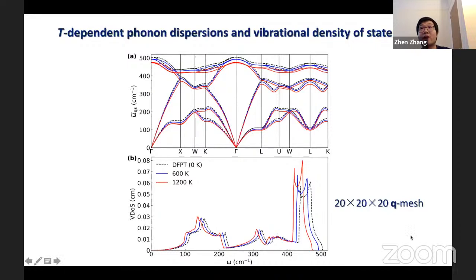Here I show the anharmonic phonon dispersions and the density of states at 600 and 1200 Kelvin, compared with those obtained by perturbation theory. The vibrational density of states were obtained with a 20 by 20 by 20 Q mesh. We can see that as temperature increases, there is clearly a red shift in the phonon frequencies.